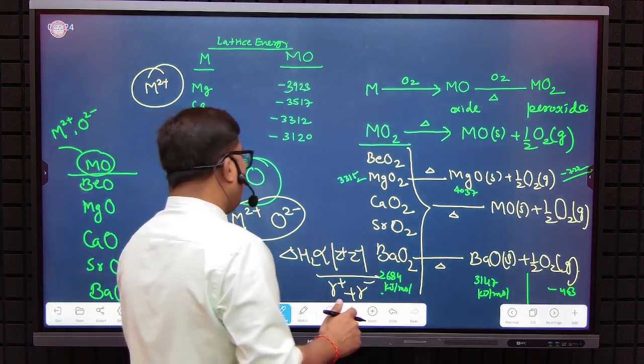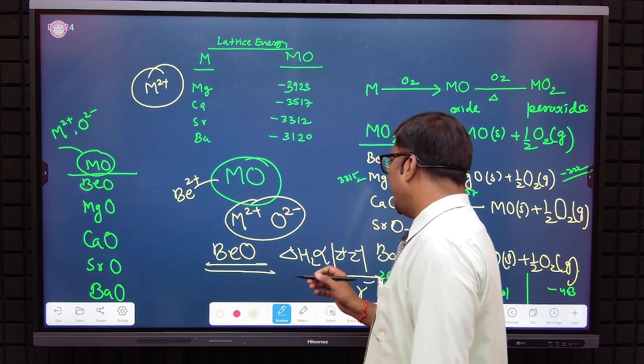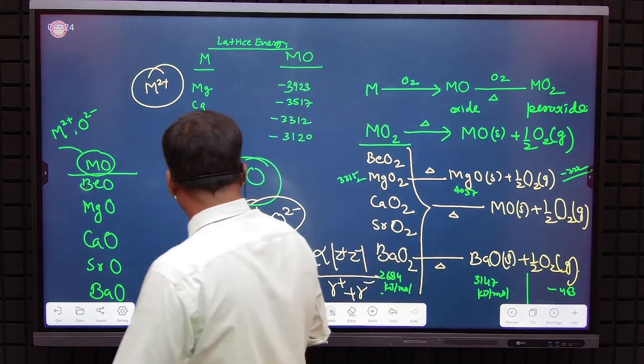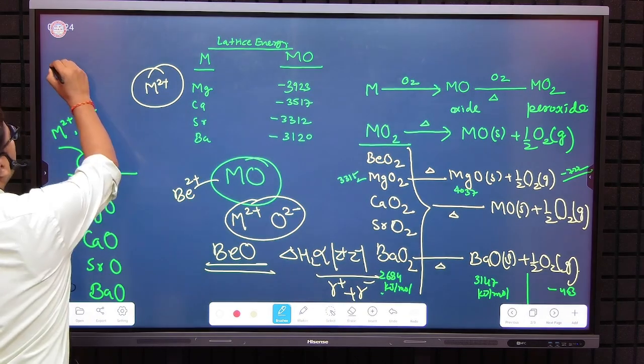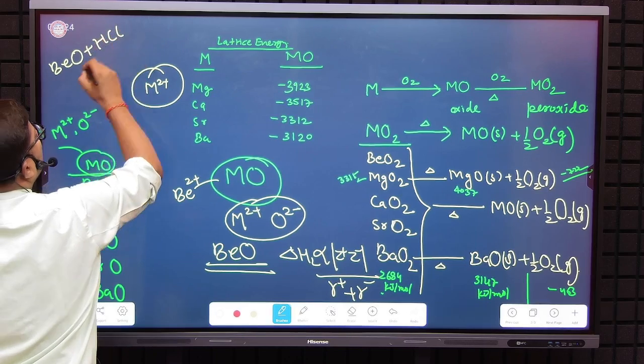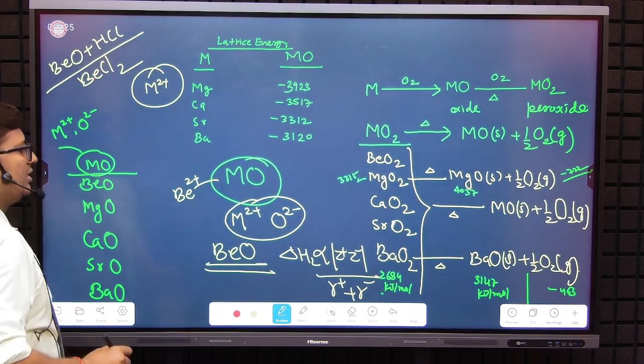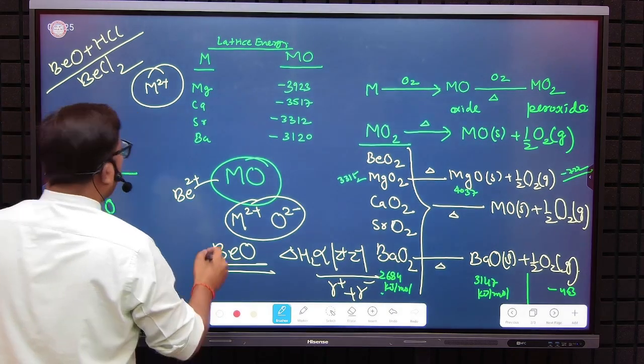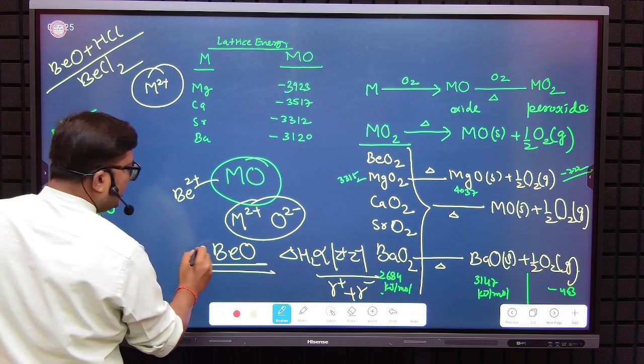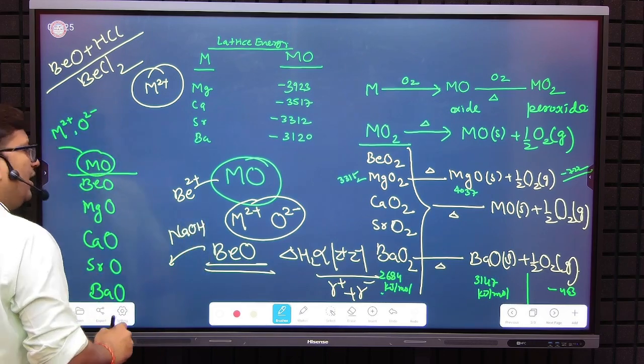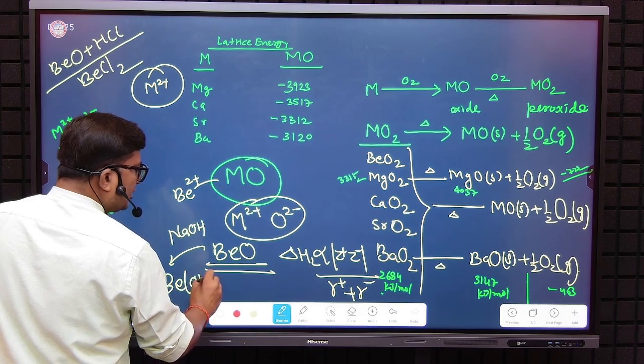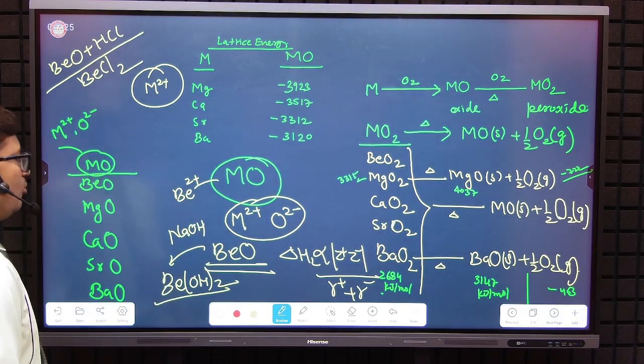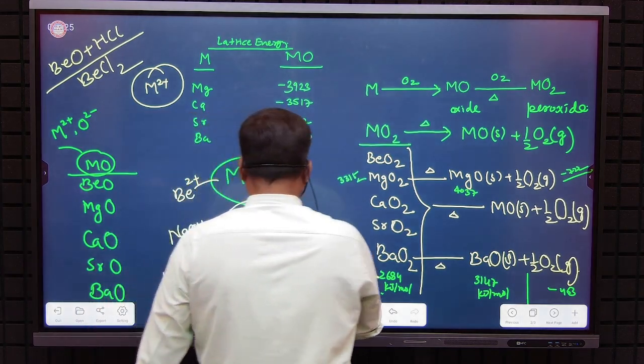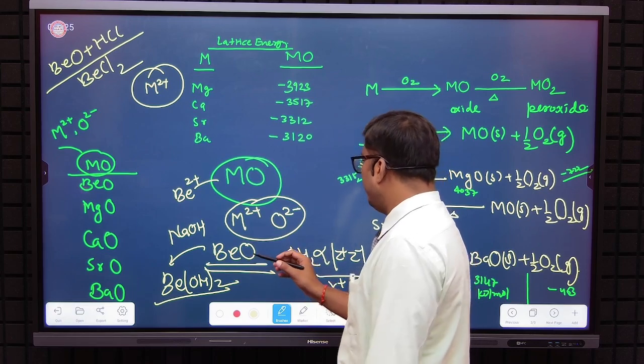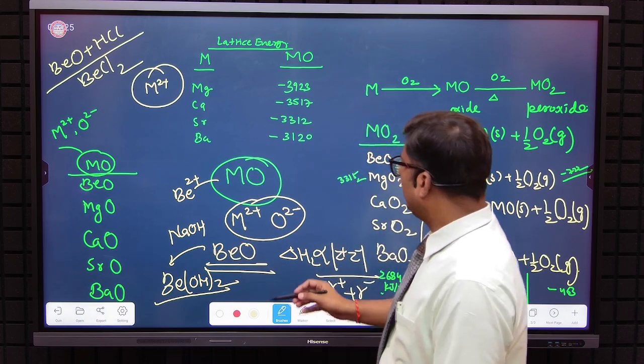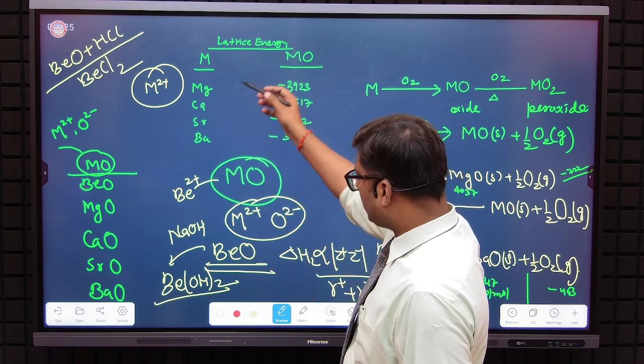This beryllium oxide is amphoteric in nature, so it can react with acid as well as base. Once it reacts with acid, it forms salts: BeO reacts with HCl to form beryllium chloride, right? And once it reacts with a base, that is sodium hydroxide, it forms beryllium hydroxide, Be(OH)2, right? More important is that, because of the amphoteric characteristics, it can react with HCl as well as base, so it is not as stable as the rest of the oxides in the series.